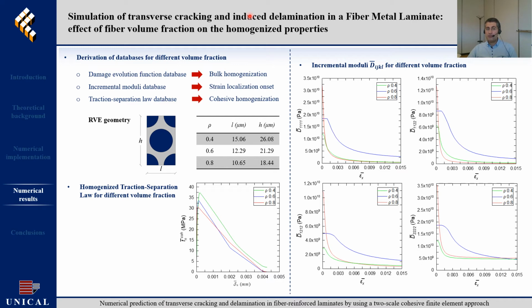Please note that the present databases are only valid for a given microstructure, so that they must be recomputed in case of different geometries and moduli contrast, as shown in this slide, where the incremental moduli and the homogenized traction separation law are derived for different values of the fiber volume fraction.